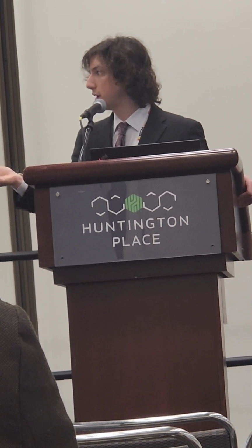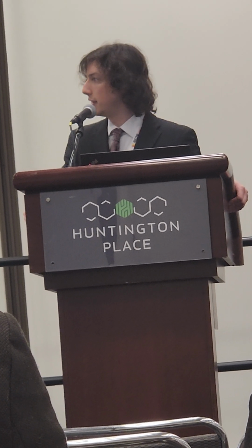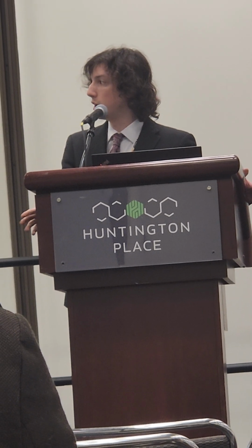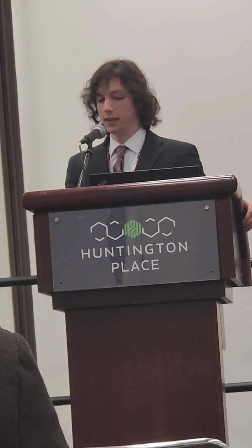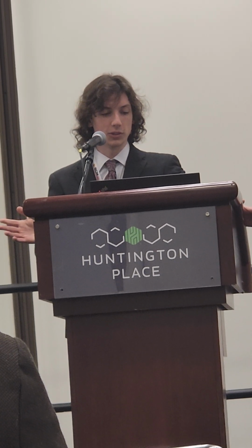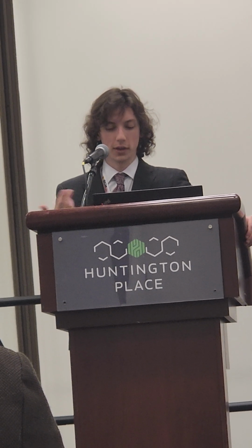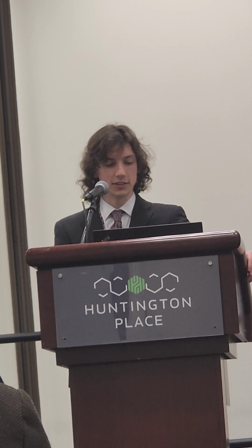So you can see clear refinement of the initial microstructure, and that led to a more refined prior austenite grain size, likely due to the increasing of total grain boundary area and allowing austenite to nucleate at more sites. So a coarser microstructure leads to a coarser prior austenite grain size, and the same with the amount of refinement you see from warm reduction.